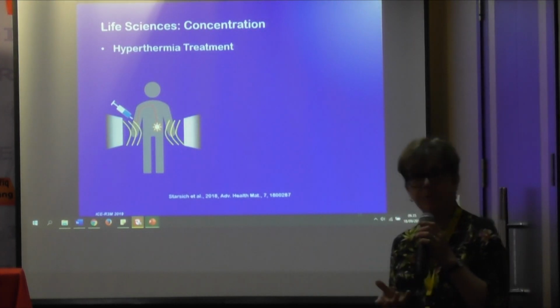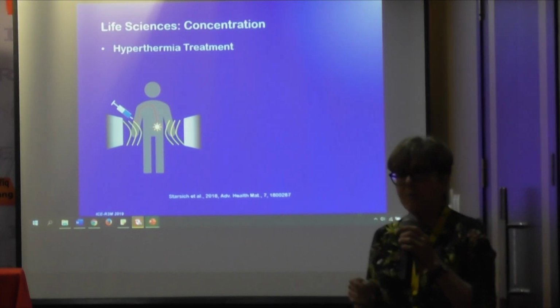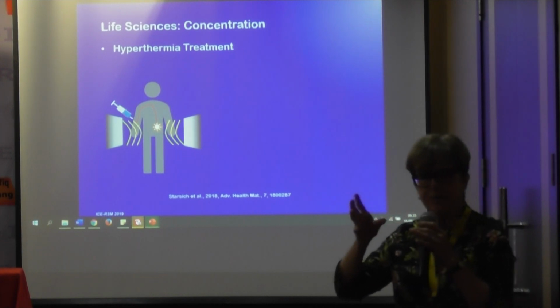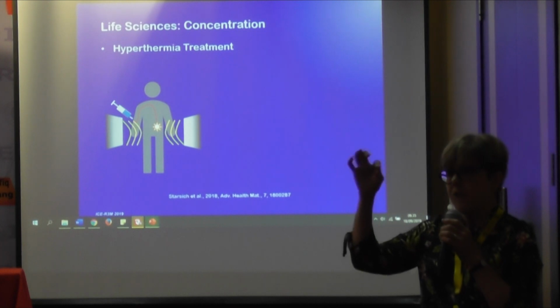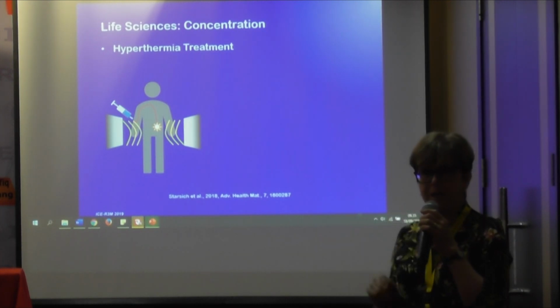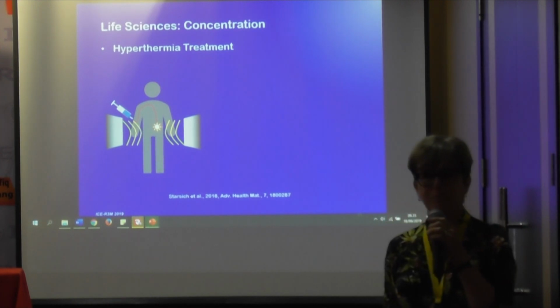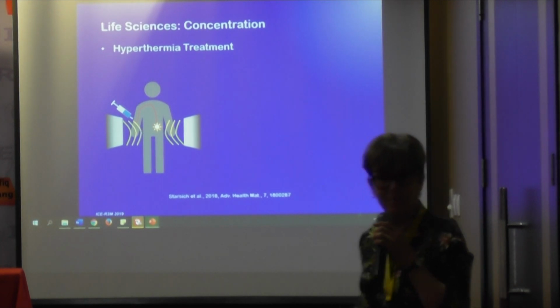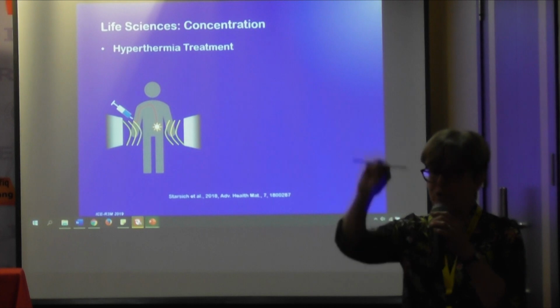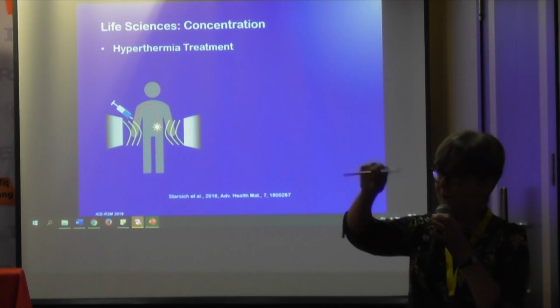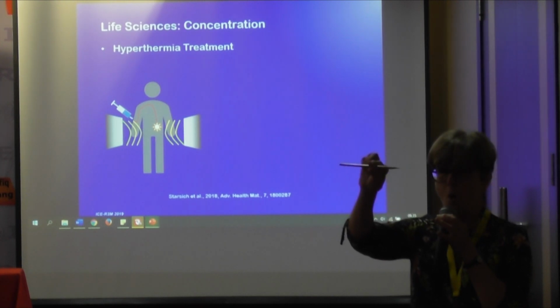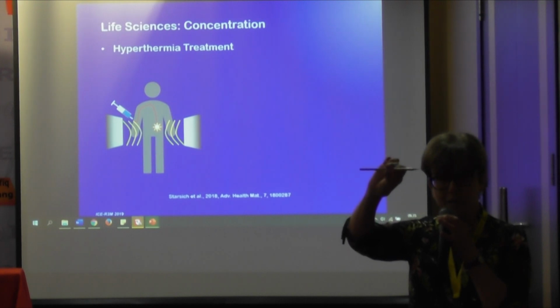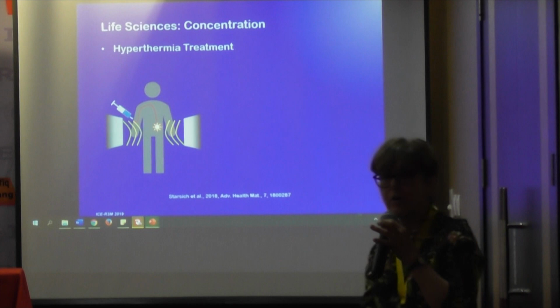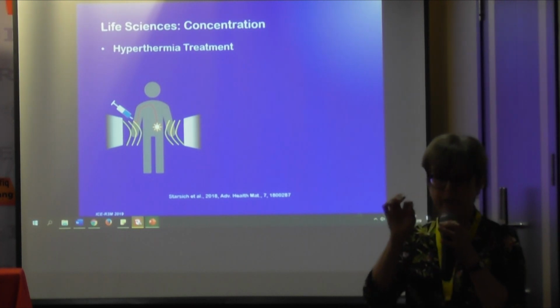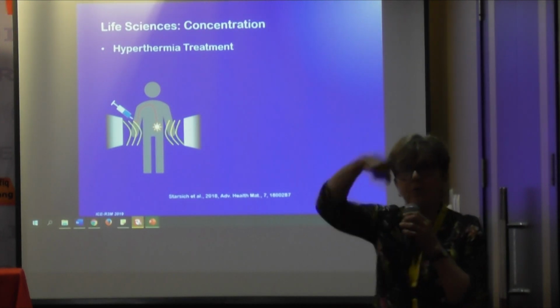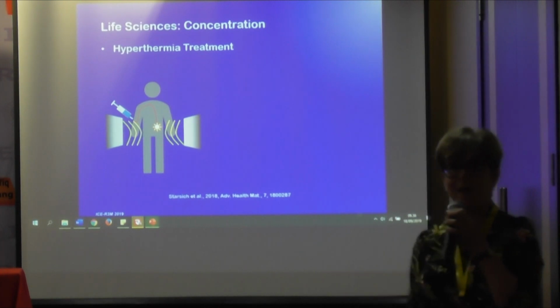Okay, a very similar treatment is called hyperthermia treatment. It's very similar to the drug targeting, and it's actually done very often in combination with the drug targeting. Once you deliver that material to the tumor, you apply an alternating magnetic field. What happens when you apply an alternating magnetic field? The particles start to move. There are 2 different types of motion. If this is my nanoparticle, either my whole particle can flip back and forth, that's called Brownian motion, or the particle doesn't really move, but the magnetic moment in that particle flips back and forth, that's Néel. Very often in these superparamagnetic particles, you have Néel motion. So your magnetic moment is flipping back and forth, and what happens when your magnetic moment flips back and forth?